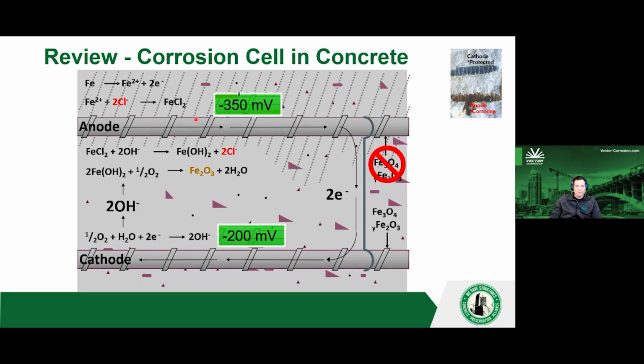An area actively corroding, minus 350 or more negative, and an area that's passive, minus 200, or more positive. And if you look at the corrosion activity, it would corrode to the most negative area. The driving potential, the difference between two of these, is what really causes this corrosion.